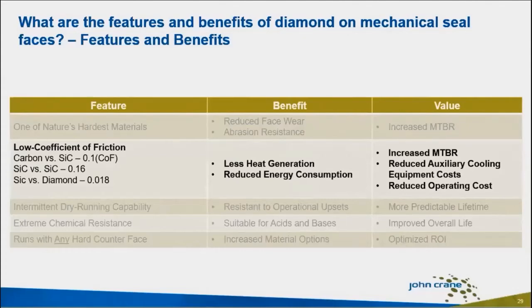Third, the reduced energy consumption, which comes from the reduced frictional losses, leads to a real reduction in electricity consumption and reduced operating costs. In fact, the power consumption savings for diamond seals is significant enough that, depending on the application, we can see payback periods of 12 months or less for the diamond treatment with respect to power savings alone.